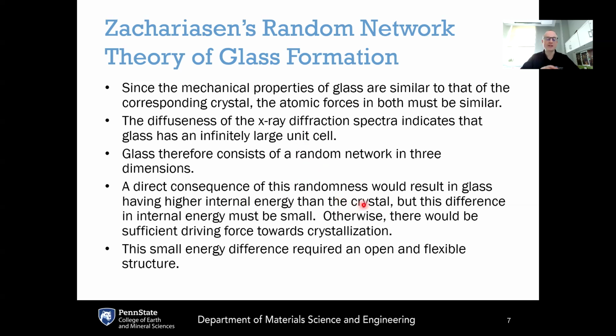Since the crystal has kind of an optimum packing of atoms together, that corresponds to a minimum in the internal energy of the structure because all the atoms are getting in optimal positions. If you move them away from these perfect lattice positions, there must be some energy penalty associated with that. And so Zachariasen is deducing that the internal energy of the glass must therefore be higher than that of the crystal. But, to continue on here, this difference in internal energy must be small.